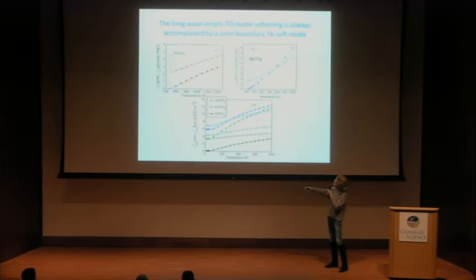Now looking at calcium titanate, it has the same tendency, but if you extrapolate the optic mode to 0, you end up at minus 40 K. So this means the system is further away from any ferroelectric properties. And now I come to europium titanate, which is the blue lines, and you see it does the same as strontium titanate and calcium titanate, but the soft mode stops at around 6 terahertz squared, the soft mode squared, and it cannot go to 0 at any finite temperature.